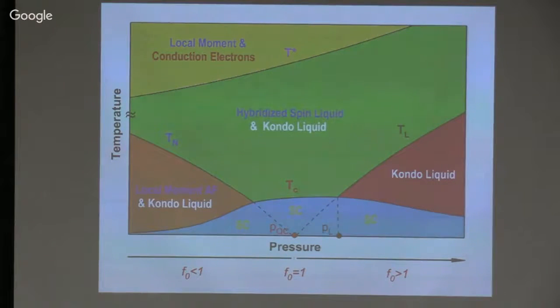At still lower temperatures, on the left-hand side, as long as F0 is less than 1, you're going to get local moment antiferromagnetism. And this is what you see. And you've got it coexisting with the Kondo liquid. So that becomes superconducting at still lower temperatures. And at the moment when F0 is such a value that the Tc for the superconducting Kondo liquid is equal to or greater than the Néel temperature, superconductivity takes over, and you cease seeing any long-range antiferromagnetic order. All you have is superconductivity. So that's what the phase diagram looks like.